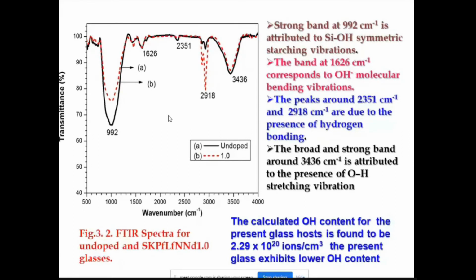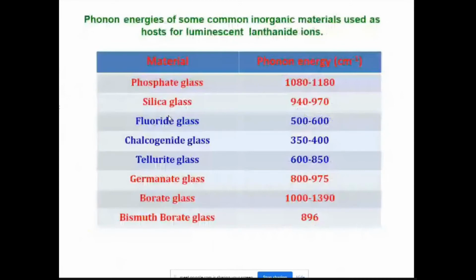And now, to see whether it's a phosphate glass, silica glass, or fluoride glass, these are all the phonon energies, a vibration. We call it a phonon energy. The solid state people will call it the phonon energy, and optical and spectroscopy people will call it vibration energy. And depending on the glass, the vibrational phonon energies vary. So you can see different glasses are having different vibrational frequencies, I mean, different phonon energies. This will help us decide whether those glasses have practical applications, particularly whether these glasses have any luminescence.